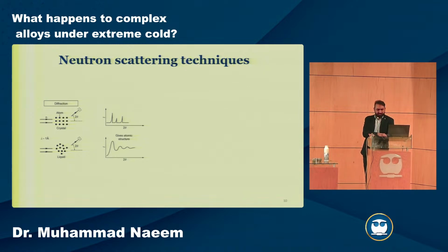And there has been a lot of work done, especially in the field of metallic glasses, where people employ this technique to do diffraction. Then Sandy was mentioning superalloys. Small angle neutron scattering is a good technique to see contrast between precipitates and matrix. You can also look at their morphology, their size, and so on.